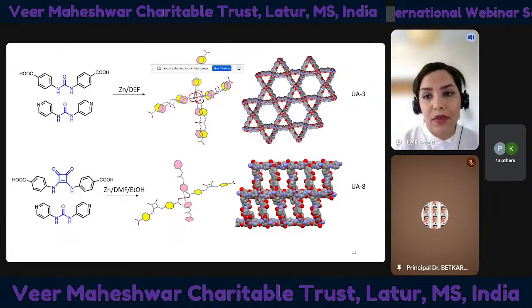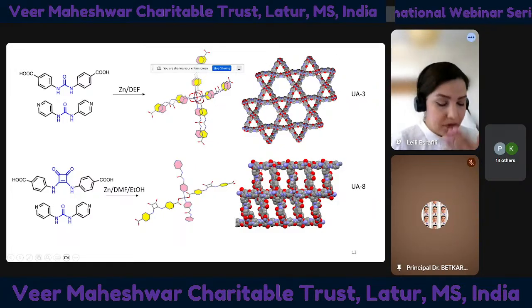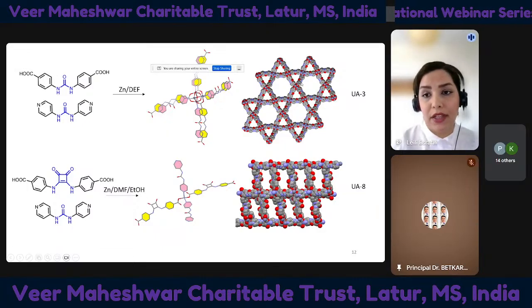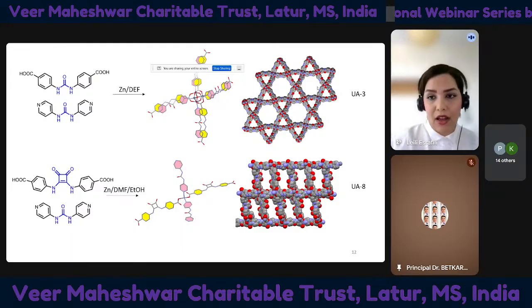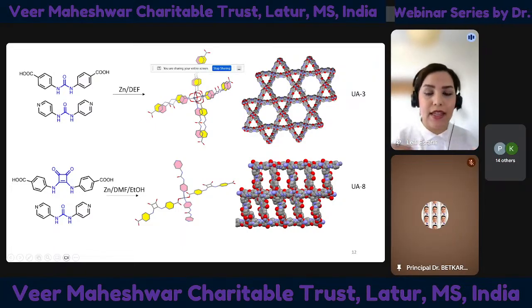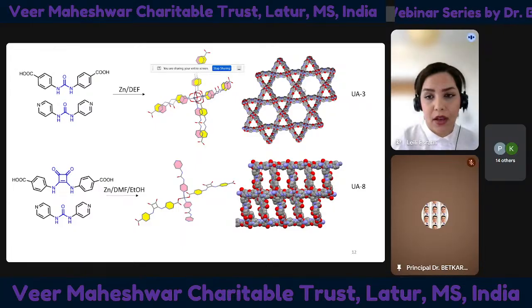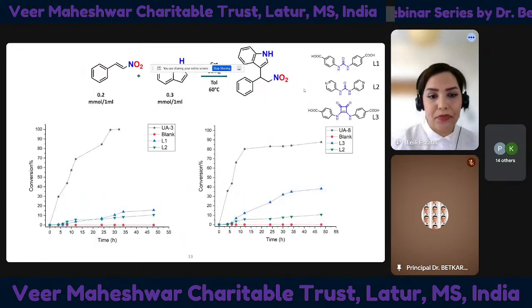And inside each of these hexagonal pores, which by the way are almost 3 nanometers, you have 12 hydrogens from 6 separate urea groups that are facing inside the pore, inside the channel.